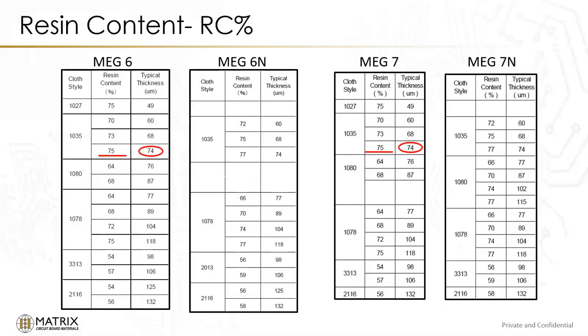And if we're looking at the end glass, I want to bring this up too, in case you're used to seeing a high resin content. If we're looking at the 74 as the thickness we're looking for, almost 3 mils, that is available on Meg 6 and Meg 7, but you'll notice that the resin content is bumped. All the low decay glass resin contents are bumped by 2%, and that's to keep the exact typical thickness in line with each of the glass styles.